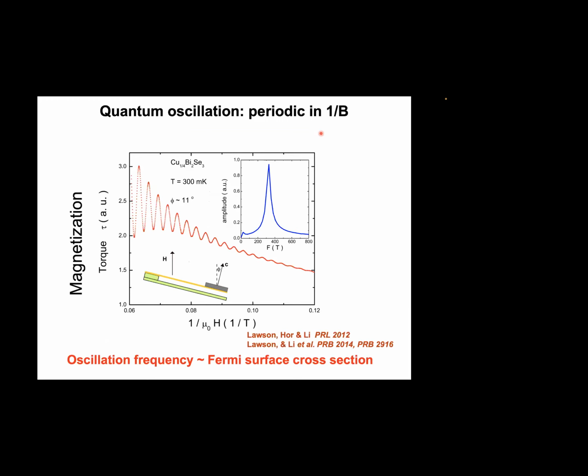the answer depends on the exact compounds, whether they are two-dimensional compounds or three-dimensional bulk compounds. But eventually we will see what geometry we're going to have for this interesting system. In this particular example, copper doped bismuth selenide, which is a topological superconductor, is heavily doped. It turns out we actually observe quantum oscillation as we have a field in plane, which means this compound, the Fermi surface is a three-dimensional Fermi surface with elongated